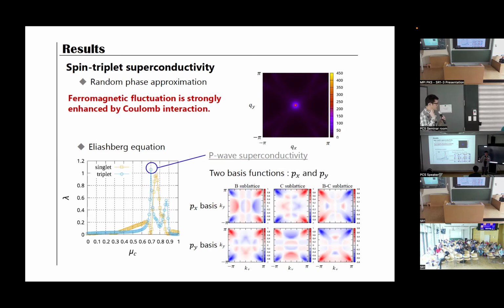We can determine the leading instability of superconductivity by looking at the eigenvalues. In this figure, we see a large peak for the spin-triplet P-wave superconductivity here. This appears when the Fermi level is close to the Dirac point, as we expected. So the take-home message of this part is the following. The topological metal with large Fermi surface and strong electron correlation may be a platform of spin-triplet superconductivities. So this is our proposal for the guiding principle for searching for spin-triplet superconductors.